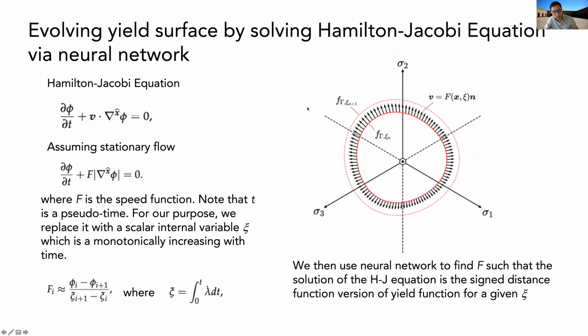But the only thing that we need to do is that in the initial Hamilton-Jacobi governing equations, we are evolving the yield surface in an artificial time. Here, the artificial time domain is represented by the scalar internal variable. So what we need to do is conduct multiple experiments in different stress paths, with different initial yielding points, and then observe, if you further load it, how much the internal variable evolves. Then we create another isocontour for a given scalar internal variable. That will give us a time-matching level set that we can solve as an inverse problem to obtain the speed functions that give us the governing equations of the Hamilton-Jacobi equations.